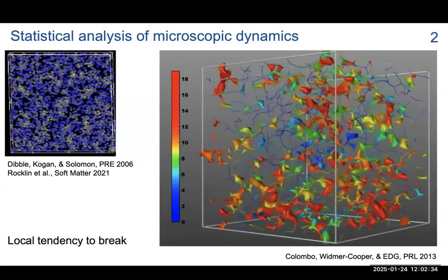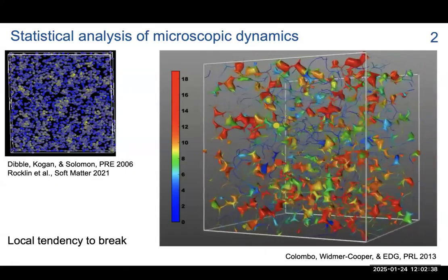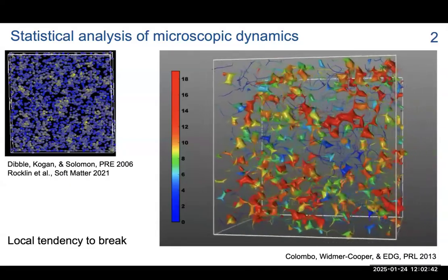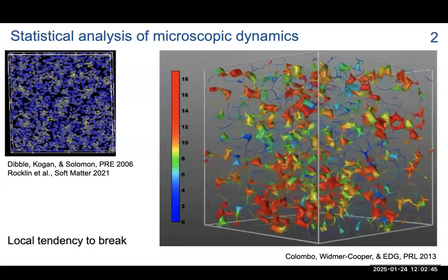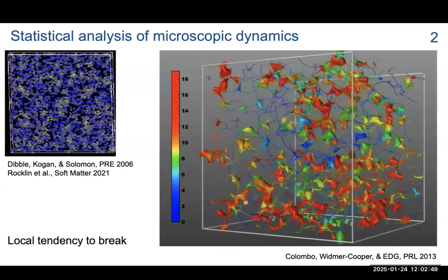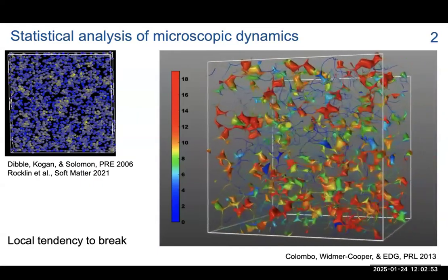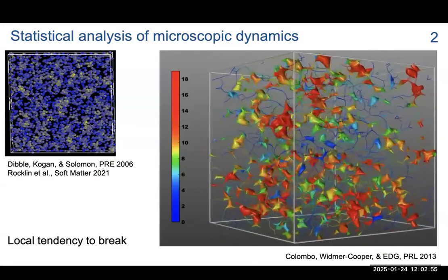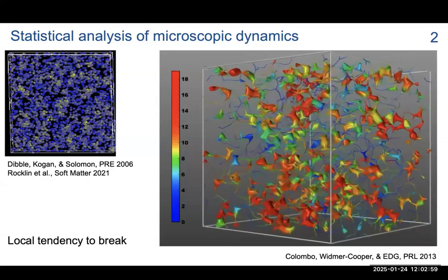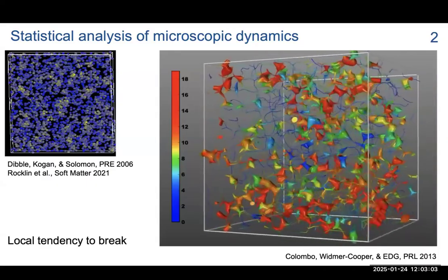So it tends to happen more in regions that are more connected, which is a little counterintuitive in the beginning, but it makes sense if you measure tension and you can see that locally the network is pulling in different directions because there are more connections there, higher order connections. And that's why you get this type of effect. That's where the tension tends to build up.